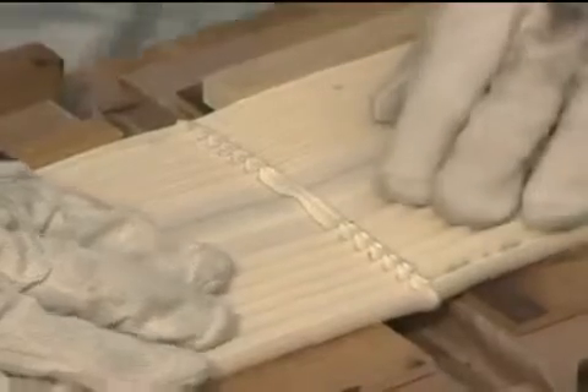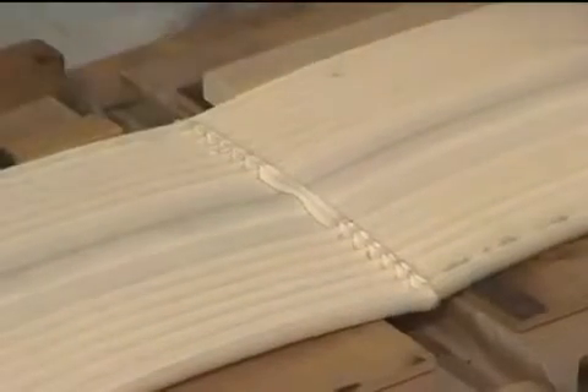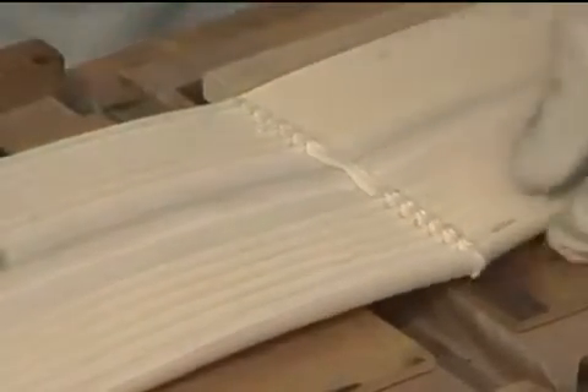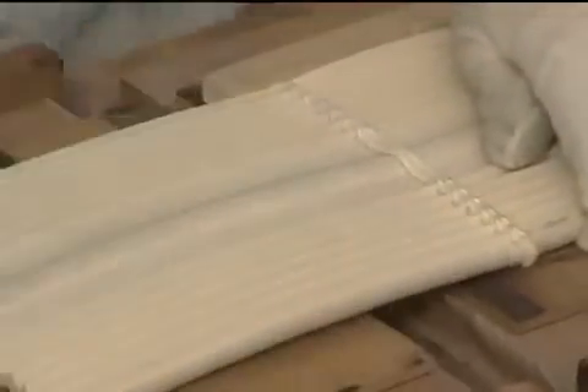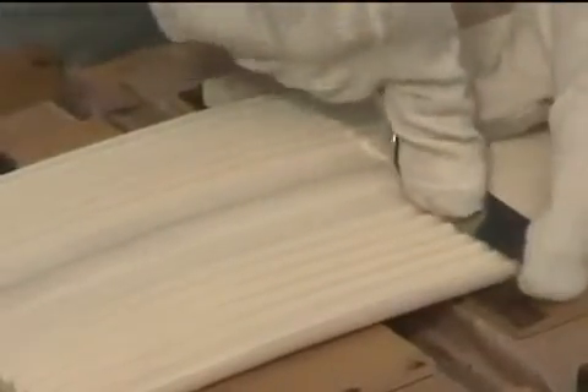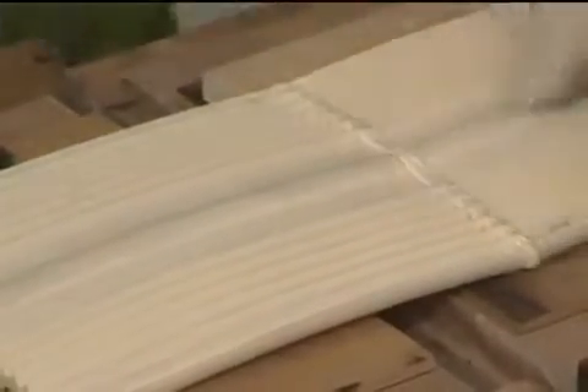Once you remove the water stop from the iron, quickly press the 2 melted ends together as fast as possible. Although pressing the water stop ends back together has to happen quickly, care must be taken to ensure that proper alignment is achieved at the weld. The water stop ribs, dumbbells, and/or center bulb should maintain continuity and alignment at the splice.